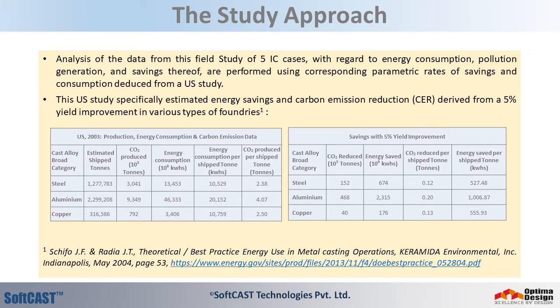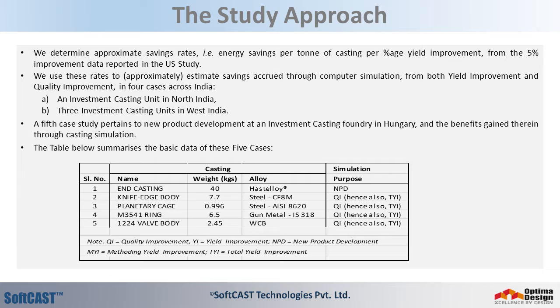The study uses findings from a U.S. research project that computed the savings in energy consumption and reduction of pollution, from a 5% improvement in yield, across a variety of cast alloys and processes. Data from 4 IC units in India and 1 in Hungary, pouring steels, nickel alloys and copper alloys, was analyzed. The castings ranged from a 1 kg steel component to a 40 kg nickel alloy component.